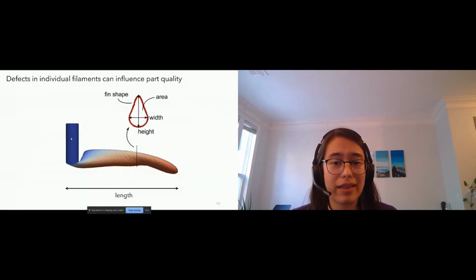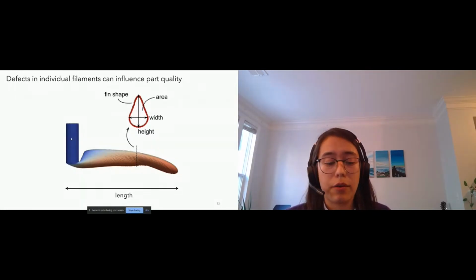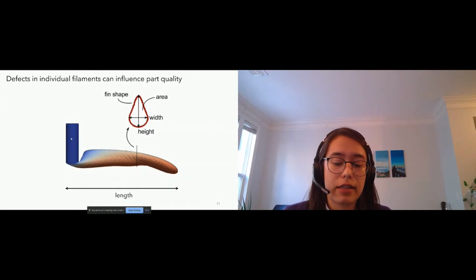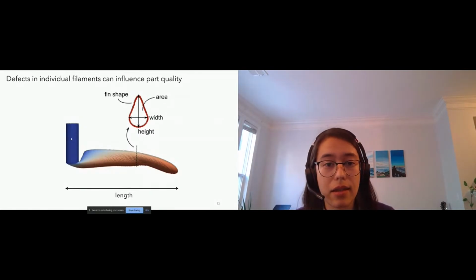I'm also going to look at the length of these filaments. So if I ask the printer for a 10 millimeter filament, I want a 10 millimeter filament. Oftentimes, if there are defects, these filaments will end up a little shorter than you intended them to be, and that's going to cause a lot of problems in terms of the shape fidelity of the part. So we're looking for a length that's exactly as long as we asked for.